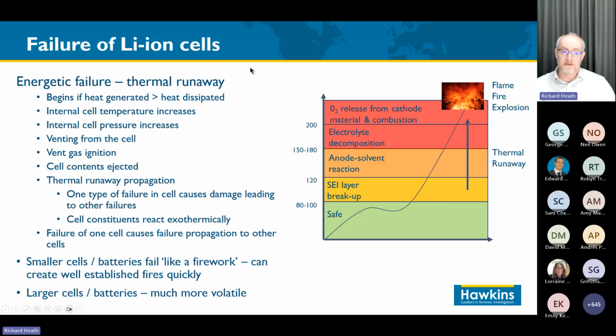But of course, there's also the more energetic failures of lithium-ion batteries, and this involves the process of thermal runaway. And this begins to happen if the heat generated inside the cell during discharge or during charging is larger than the amount of heat that can be safely dissipated. And so the internal temperature in the battery starts to increase. And the chart on the right is showing that there is the safe area for the cell, which is below about 80 to 100 degrees.